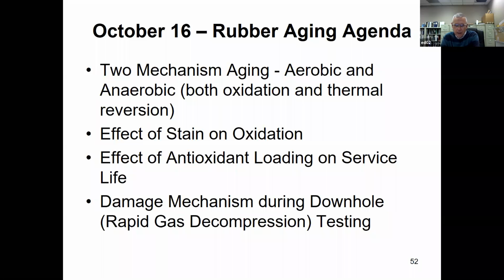The oxidation rate is significantly affected by the sulfur content in the compound. The higher the sulfur content in the compound, the faster it oxidizes. So I think the sulfur is somehow participating in the oxidation mechanism. It reacts faster than the carbon, so to speak. As far as the chemical structures, I don't know if you were asking about that. Presumably they're similar between efficient cure and conventional cure, but definitely the conventional cure will be oxidizing faster than the efficient cure.